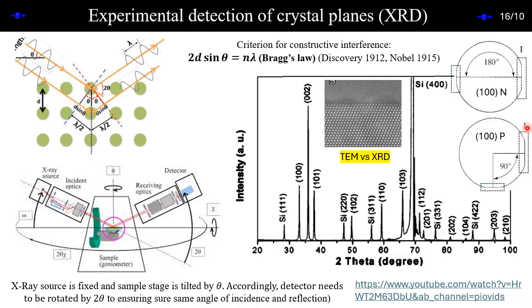You make it very thin. Say 10 nanometers, 10, 20, not more than that. Then you illuminate this surface with an electron beam. Later on you will see the electron as wave-particle duality. Electrons are particles, but they also have a wave nature. We'll see that in the next class: a wavelength lambda is associated, and you can tune it with the energy of the electron, and this can be much smaller than the atomic dimension.